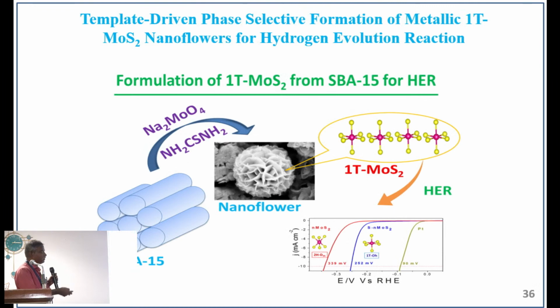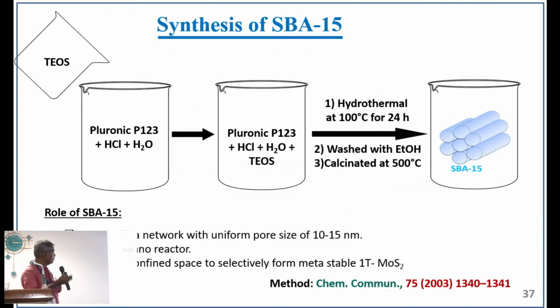So what we have developed here is template-driven phase-selective formation of 1T MoS2 nanoflowers for hydrogen evolution reaction, because we used a nanoscale template to grow the material inside the template, and after that we demolish the template and recover the material. So this is a template-based process. In this case we use silica, SiO2, the well-known material SBA-15. It's a commonly available material for any industrial-scale application.